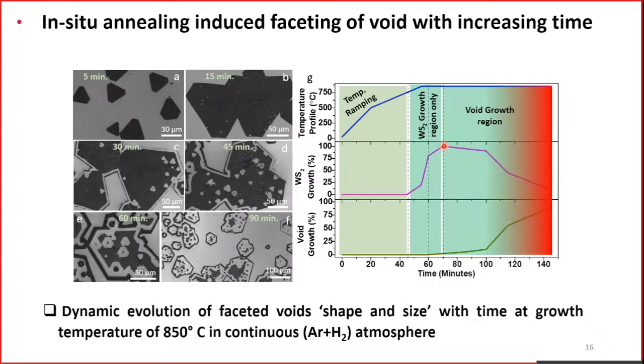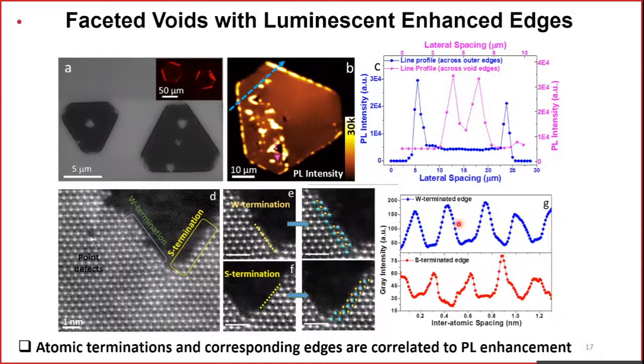After that, if you keep it further for 10 minutes, 15 minutes, what will happen? Your growth will not increase further. Rather, your voids essentially keep growing. So you can see void growth is increasing and WS2 is decreasing. These two are essentially complementary in nature.